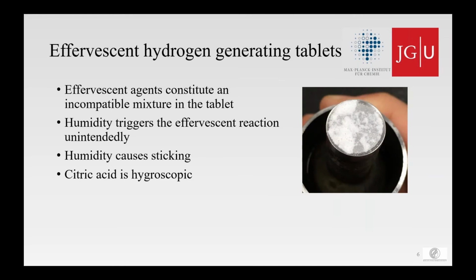Effervescent tablets are usually really moisture labile, because technically effervescent agents constitute an incompatible mixture within the tablet. And humidity also triggers these effervescent reactions that I talked about unintendedly. And during manufacturing, it also can cause sticking if it's very humid. For example, you see it on the right, sticking occurring during compaction. And moreover, this is all worsened by the fact that citric acid is hygroscopic. So yeah, as you can imagine, this is a really problematic formulation to manufacture and store.